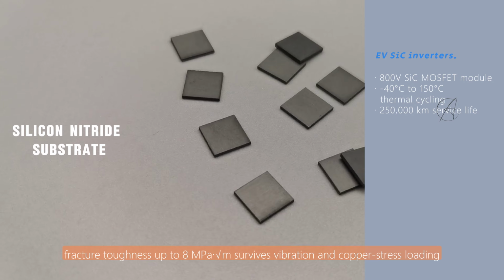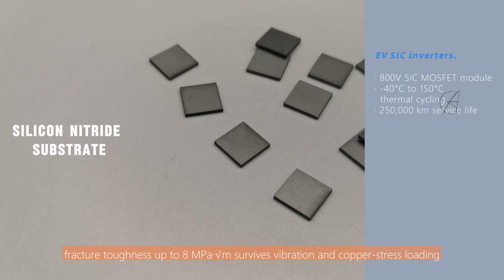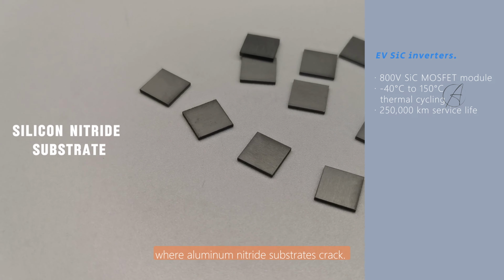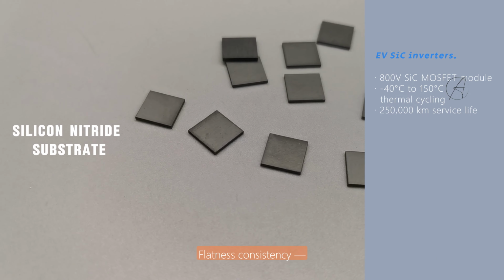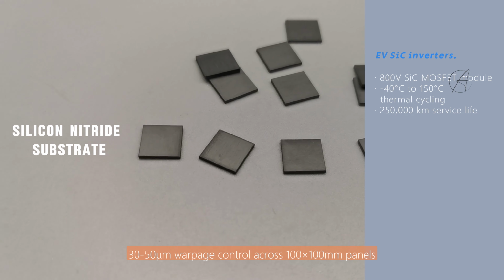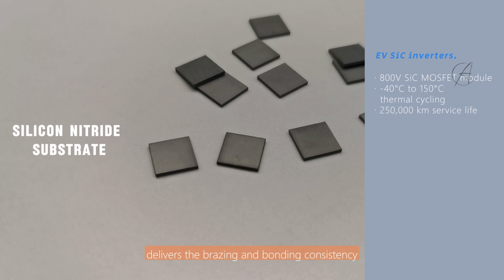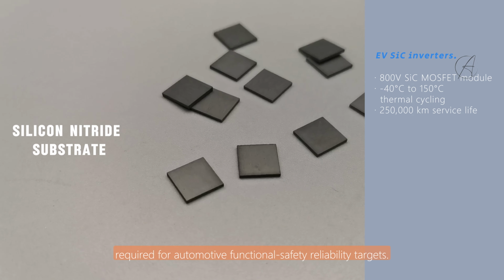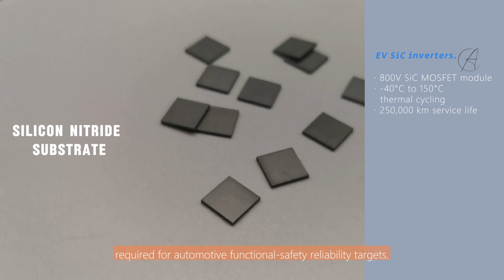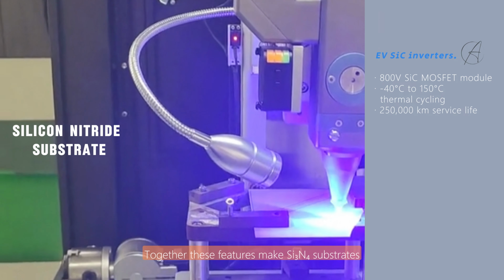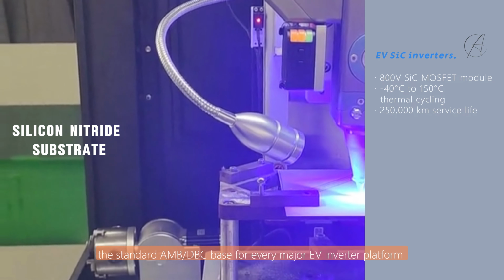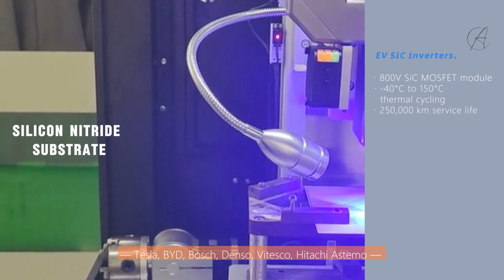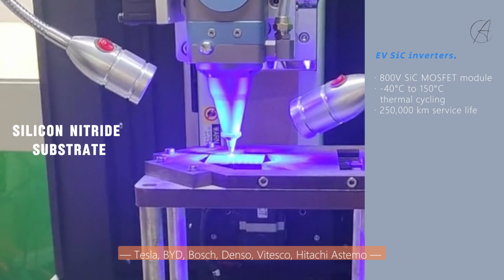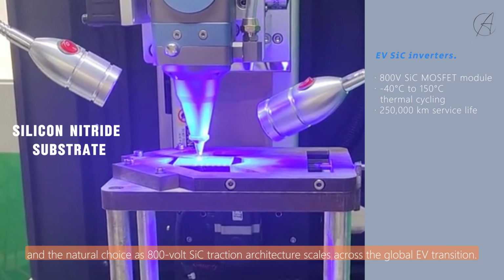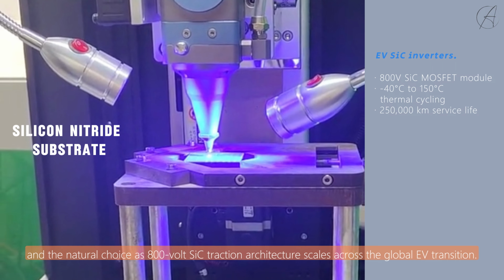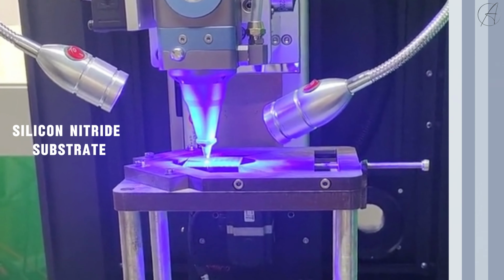Mechanical reliability. Fracture toughness up to 8 megapascal root meter survives vibration and copper stress loading where aluminum nitride substrates crack. Flatness consistency. 30 to 50 micrometer warpage control across 100 by 100 mm panels delivers the brazing and bonding consistency required for automotive functional safety reliability targets. Together, these features make silicon nitride substrates the standard AMB or DBC base for every major EV inverter platform. Tesla, BYD, Bosch, Denso, Vitesco, Hitachi Astemo, and the natural choice as 800-volt silicon carbide traction architecture scales across the global EV transition.